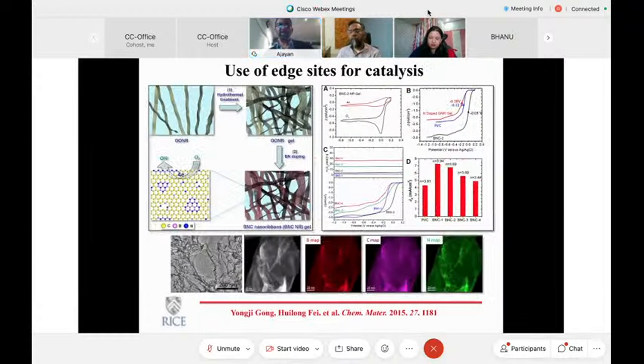The other option is to make nanostructures from these 2D layers. And again, lots of work is being done in making ribbons or quantum dots of graphene and similar 2D structures. And once again, because of the large number of edge atoms sitting in these ribbons compared to flat sheets, you have much higher activity in many of the chemical reactions. So, edge sites are important for reactivity in these materials, obviously.